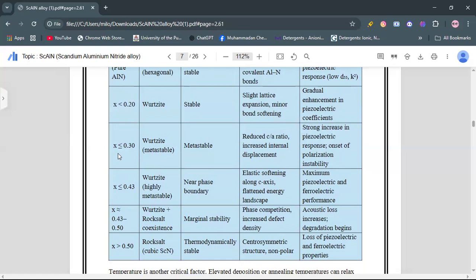When the concentration is 0.43 to 0.50, acoustic loss increases and degradation begins. And at concentrations above 0.5, the alloy exists in the rock salt structure, which is thermodynamically stable, but loss of piezoelectric and ferroelectric properties occurs.